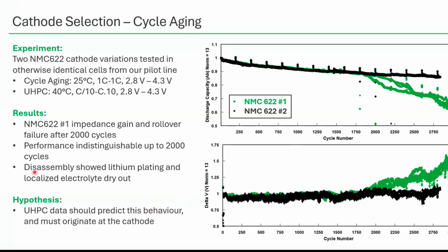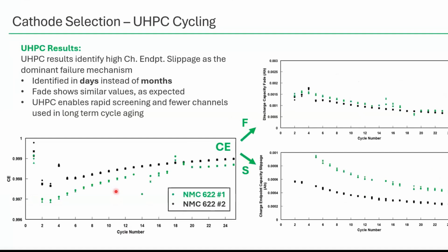Some disassembly showed some lithium plating, localized electrolyte dry out. So clearly something's happening that really must originate at the cathode, because all these cells were made and tested the same way at the same time. So our hypothesis is that UHPC data should identify this relatively quickly.